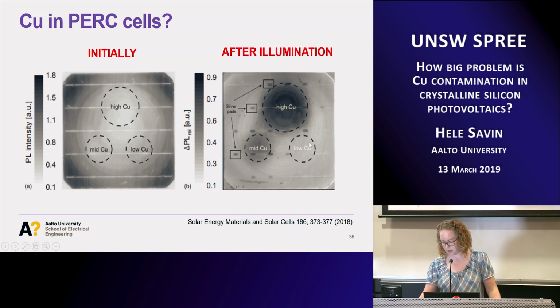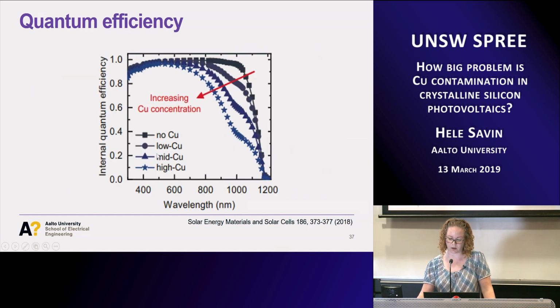Interesting is that maybe here in the low copper concentration we don't see it. So this was one thing we wanted to see, is there a threshold copper concentration, so that you can have a certain amount of copper before it becomes trouble. So based on PL, this seems to be the threshold, but if we actually do the EQE measurements on this location, and with all these locations, even with these low copper spots which didn't show any degradation in PL, in EQE it's actually quite a dramatic change. It could be the backside, but I believe this is the bulk degradation.